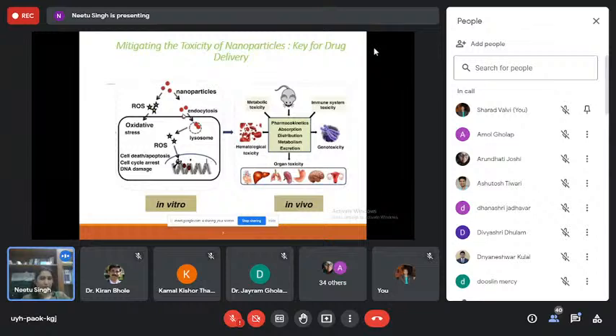Another thing which is important to understand is that in the host, or in humans, reactive oxygen species are quite commonly generated. These reactive oxygen species, ROS as we call them in short, are one way of getting rid of or denaturing proteins which are not important. So, getting rid of debris or unwanted proteins, ROS is used to degrade the products. Now, the nanoparticle surface can act catalytically and increase ROS production. Because of the increased ROS production, there is oxidative stress in the system, and it can cause DNA damage and things like that. And this ROS becomes very, very dangerous. So, this is also a reason for toxicity.